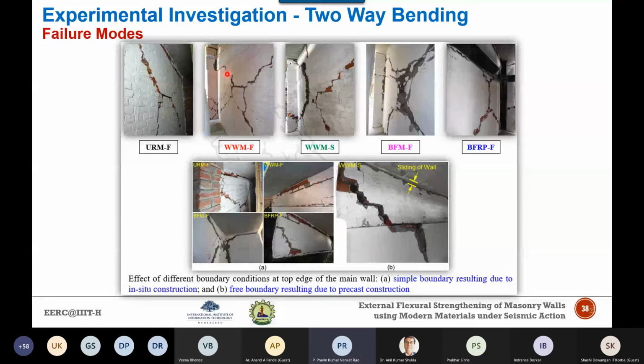See, this is my band, and all the cracks are occurring just beneath the band, whereas at the top, there are only the horizontal cracks. Here you can see in the top photograph, just above the band, there are no diagonal cracks, only horizontal cracks. Whereas classical diagonal type crack patterns have been developed just beneath this welded wire mesh. So it means that in this case, the welded wire mesh has not ruptured.